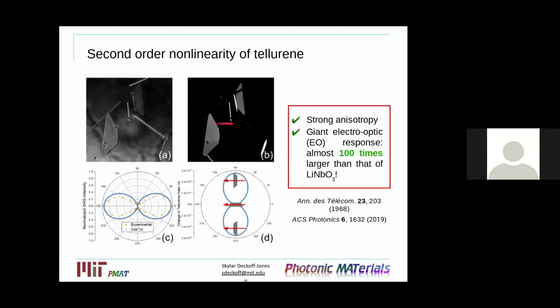But we also see that when our light is polarized along this direction, horizontally on my screen, we see only certain flakes light up. And when we change the polarization along the other direction, the other flakes light up. So this has to do with the strong anisotropy in that chain-like structure of the tellurium. And so we can model and experimentally measure the second harmonic generation as a function of the orientation. And from this, we now know, if we wanted to create an electro-optic modulator, how we would want to orient our electric field to achieve the largest Pockels electro-optic response in our material.